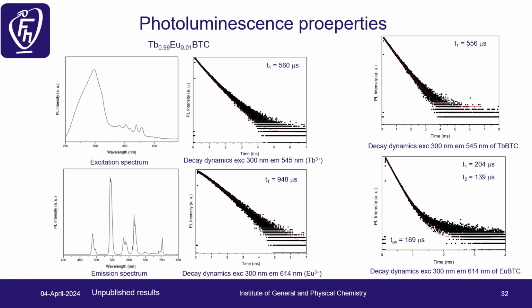PL, what we saw here is this is 1 mole percent doped europium to terbium, so we excited in the ligand, and we got this emission nicely. You can see the peaks of terbium, europium. In this case, almost white light we got. We can use this also for temperature sensing. I didn't do it yet.